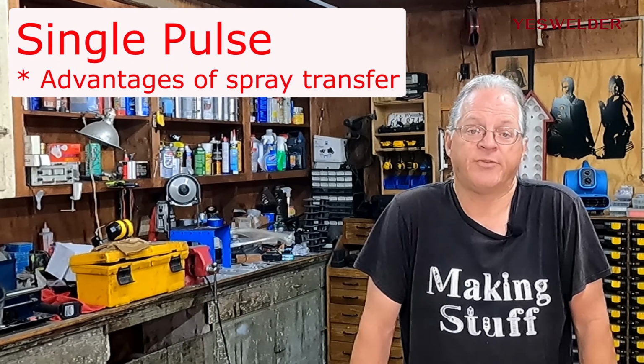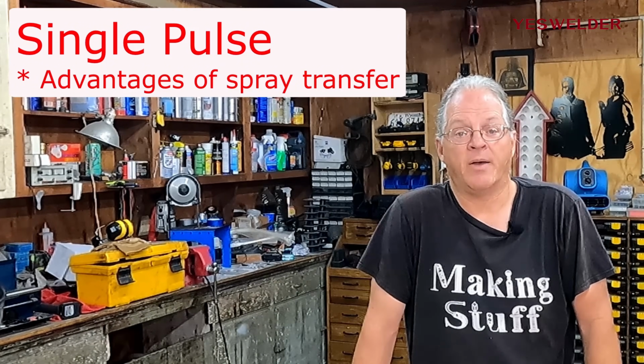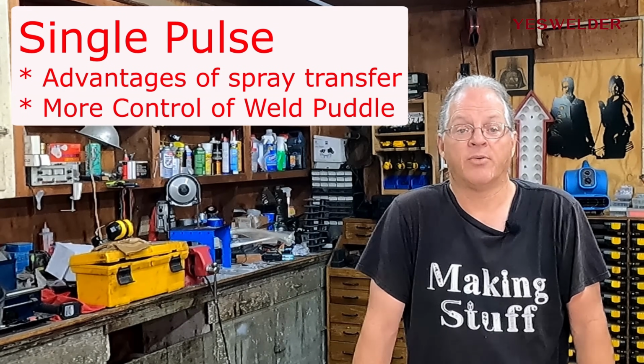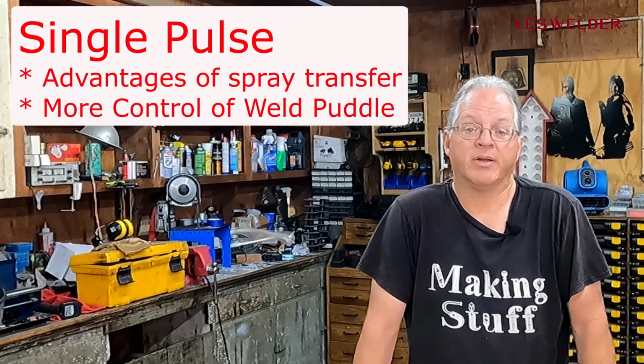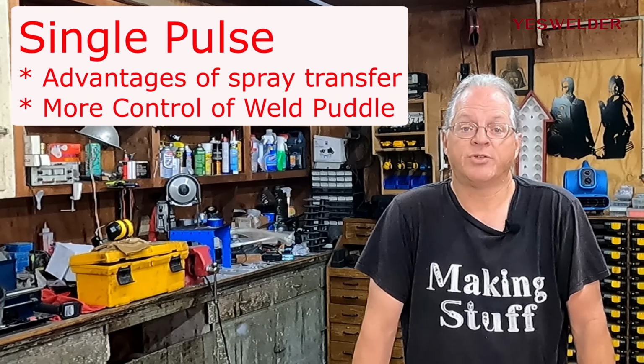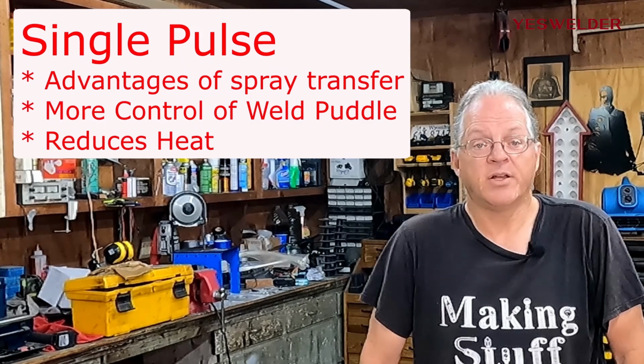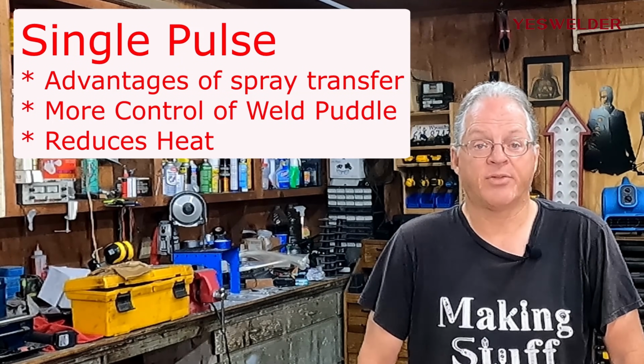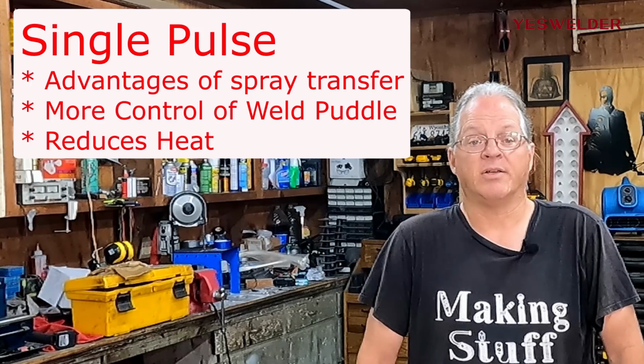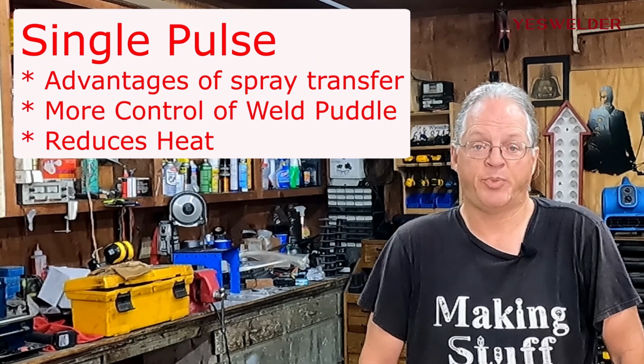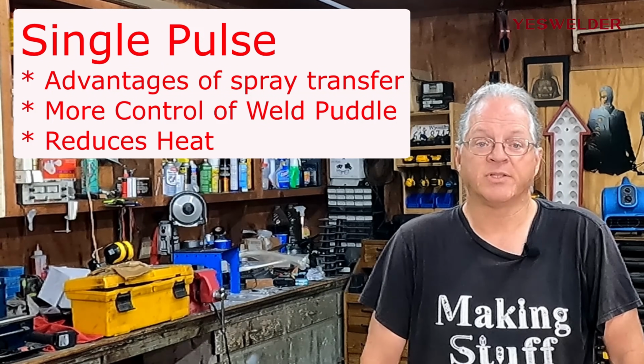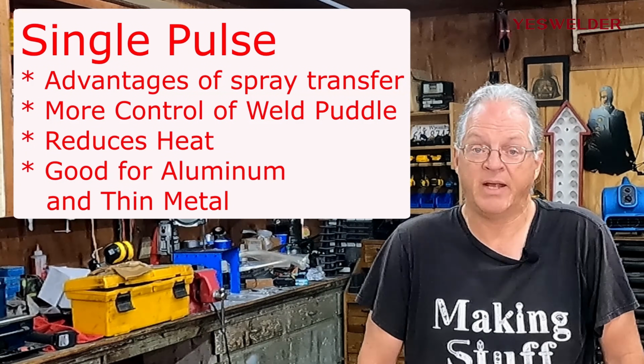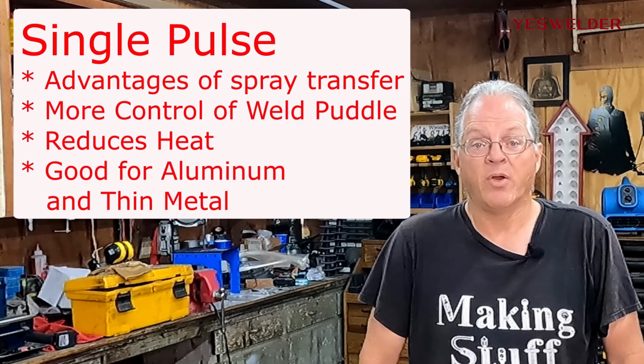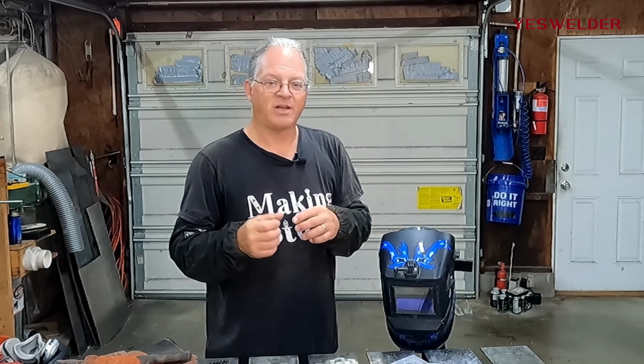By adding this pulse to the current, it will allow the use of the spray transfer mode, but by reducing that current on the background level, it makes the current lower in intensity and also allows the puddle to solidify faster, giving more control over the weld puddle. Also, since the current doesn't stay at that peak setting through 100% of the weld, it also reduces the amount of heat that is put into the workpiece. This makes pulse MIG welding great for aluminum and thin metal, where it can be easy to warp or burn through your workpiece.